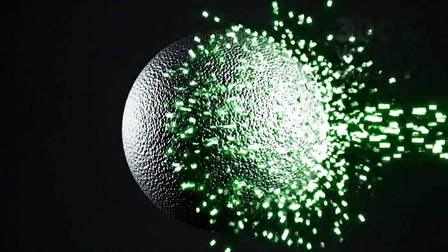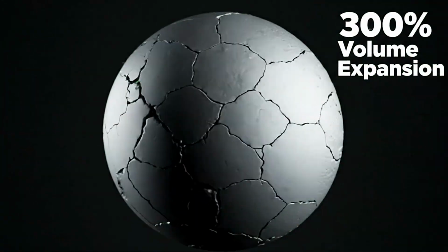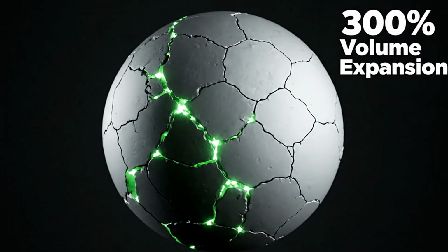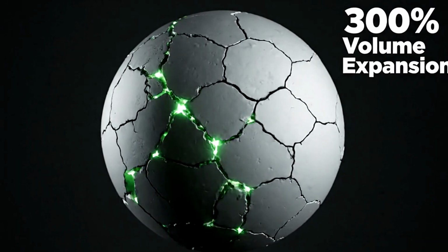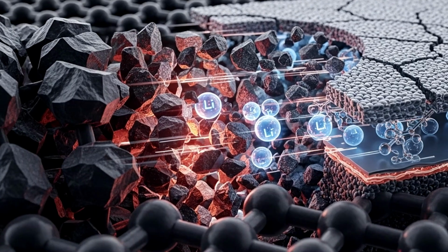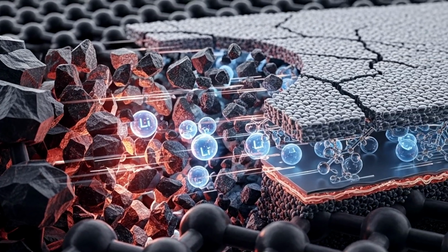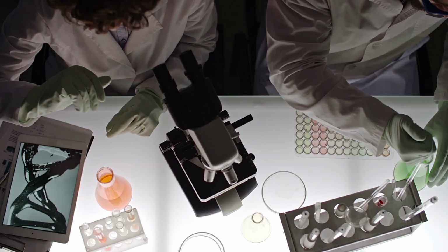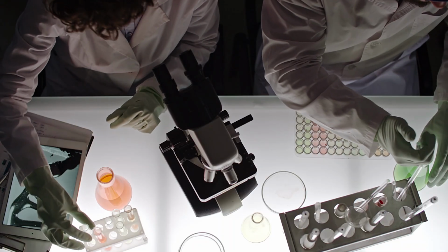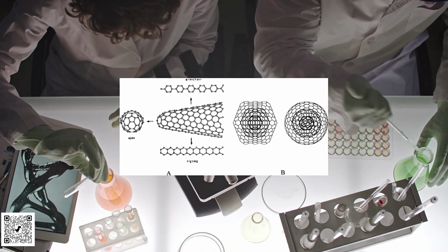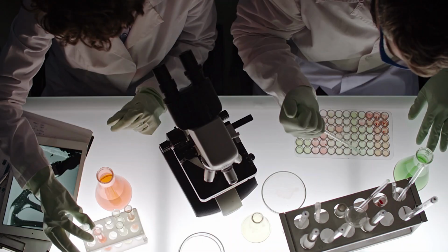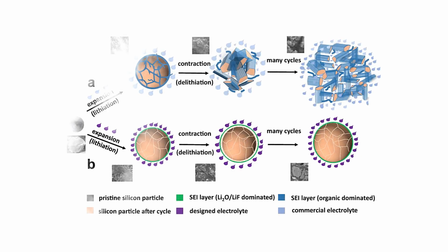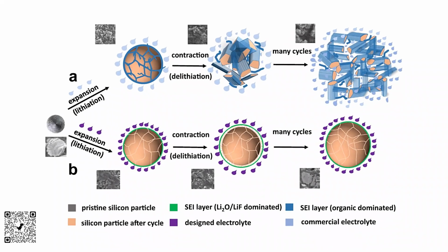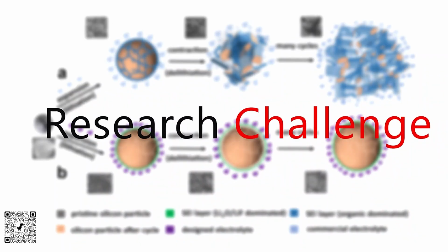When fully lithiated, it swells by about 300%, cracking like a shaken concrete block. Each charge cycle pulverizes the silicon and breaks the protective SEI layer, slowly killing the battery. Engineers are fighting back, for example, using silicon nanostructures or silicon-graphite blends to absorb the stress. But the volume change puzzle makes pure silicon anodes an ongoing research challenge.